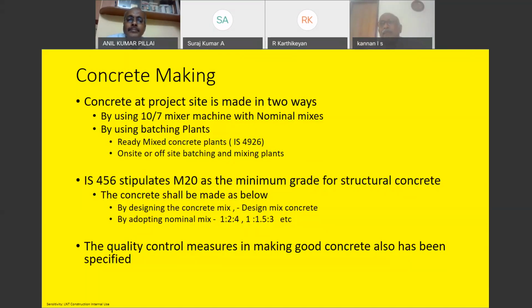See, for instance, for 1:2:4 concrete, you use a cement content of 6.4 bags, say 320 kg of cement. And we say 1:2:4 concrete is equivalent to M15 grade concrete. With the same 320 kg of cement, if you go with a design mix concrete and the mix design is done well, M20 grade can be produced.